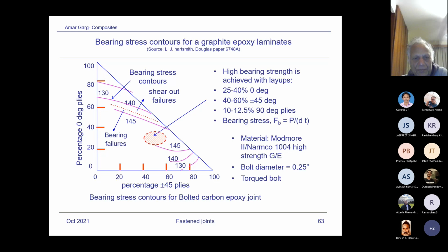Okay, now this is showing the data for the bearing stress contours for graphite epoxy laminates, which I have taken from L. J. Hartsmith's paper. It shows percentage 0° plies and percentage 45s, and these bearing stress contours, 130, 140. I think these have slipped; this should be 130 here, and say 145, 145. So depending upon that, you can see here that you are achieving highest bearing strength allowable somewhere here, which is lying between 40 and 60%, somewhere around 50%, and zero around 25%.